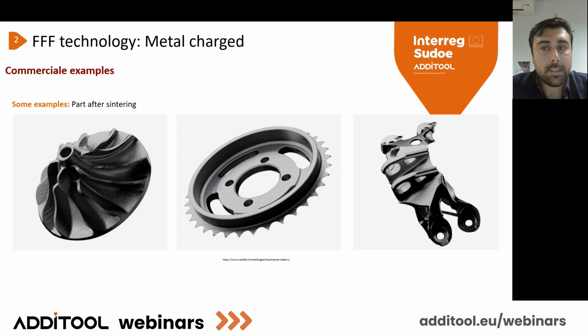Okay. Here you can find some examples that you can find on the market. So parts after sintering with different geometries, different complexities, and it works. If someone can do it, it's possible, and we can find them directly on the commercial market. However, what we analyzed is that the parts are little and flat. You have the plate, and it's not so high. It's a little part, and the thicknesses are equal. If you take a look at the three parts, the thickness of each wall is equal. So it is easy to debind when you have equal thickness on different walls. So it works for little parts.